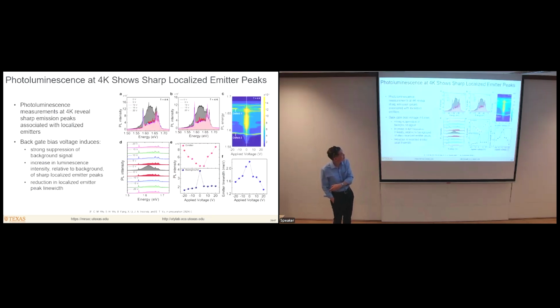We can then go from here and look at photoluminescence at 4K. And what we see in this case is the well-known emergence of these very sharp luminescence peaks that are typically associated with light emission from localized emitters, associated with defect levels. And these are often associated with single photon emission. There's an interesting dependence of the behavior of these localized emitter peaks on the bias voltage that's applied. When we apply this bias voltage in either polarity, there's a large reduction in the broad background photoluminescence, an increase in the intensity of these localized emitter peaks relative to the background, and a reduction in the line width, all of which are favorable for single photon emission.